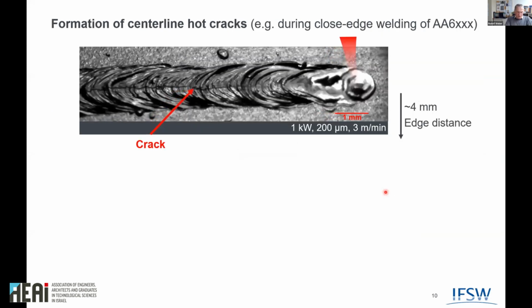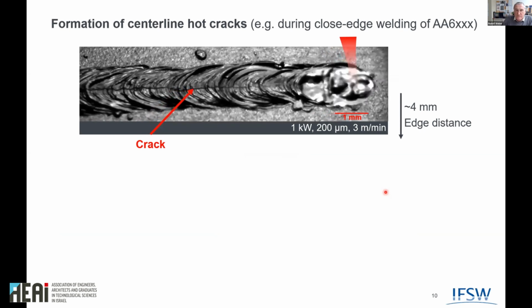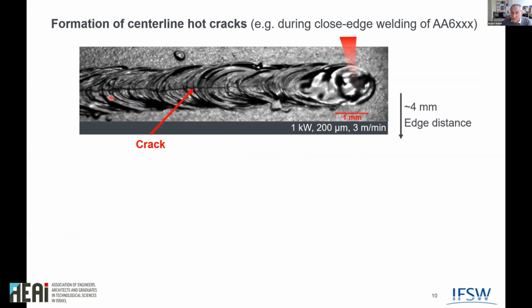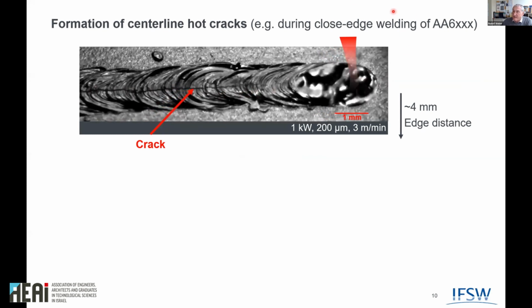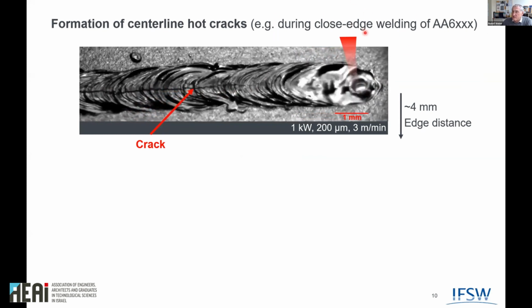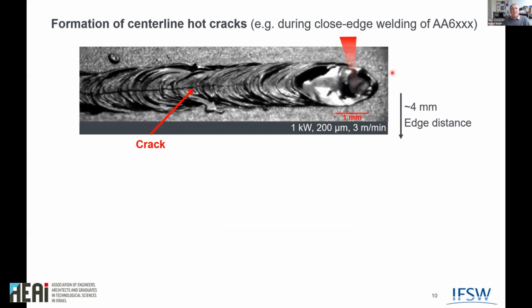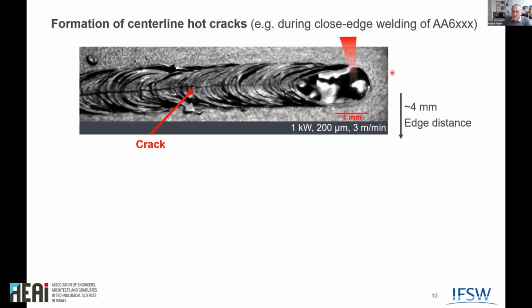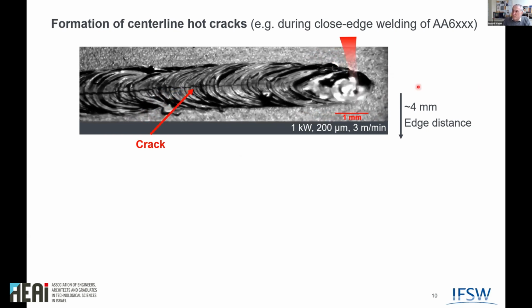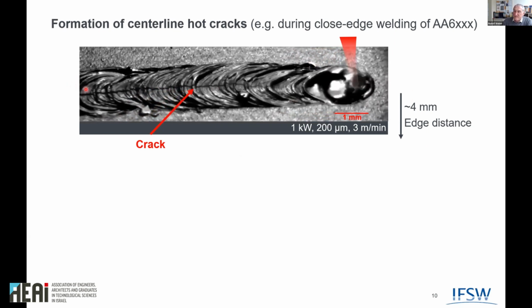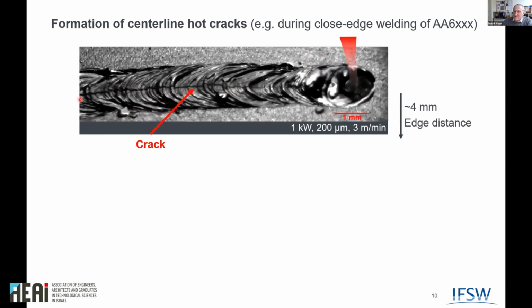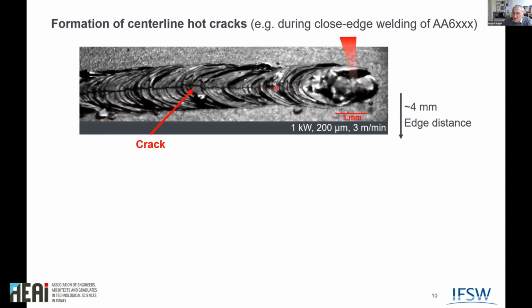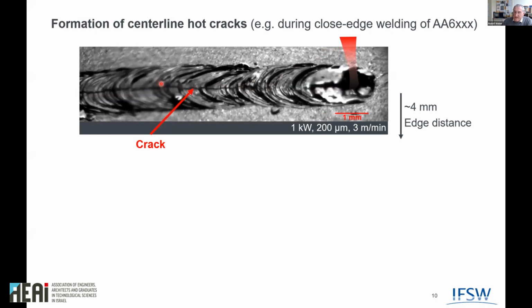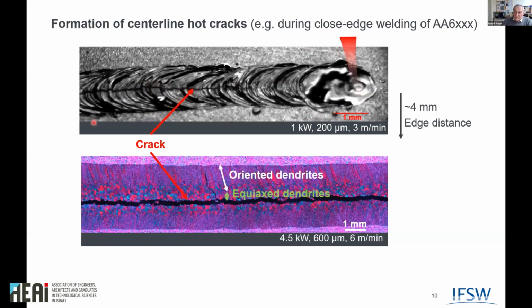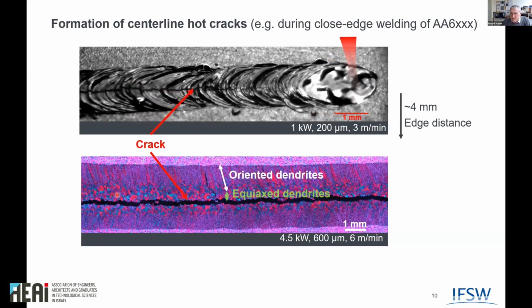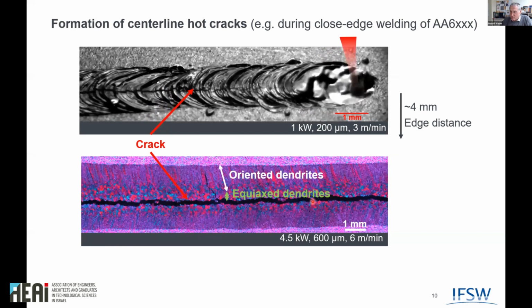The second thing I would like to show you is the formation of hot cracks, which is also a quite important issue that mainly happens if you do close edge welding of aluminum alloys, which is mainly in car doors. Modern car doors are made of aluminum. If you are close to the edge in a few millimeters distance, that's what happens if you do just a straightforward weld. You can see that really very shortly after the solidification, a very nice, very big crack opens. You can make this cross section with Barker etching. Then you can see the material structure which comes up.